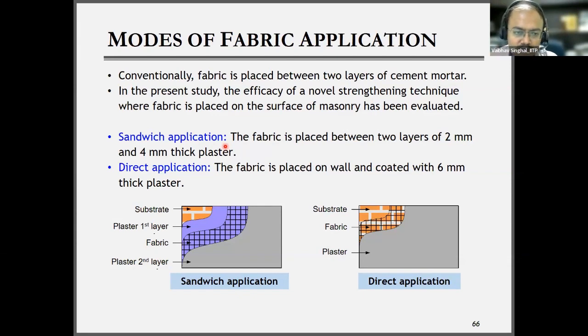So the first layer of plaster was 2 mm. Then we applied the fabric, and another layer of plaster was 4 mm. And in the direct method, we have directly applied the fabric over the surface and then put a plaster of 6 mm total thickness. So total cementitious matrix thickness was 6 mm throughout for all the specimens. Now in this also we have tried with anchors. So both techniques have anchors and without anchors.